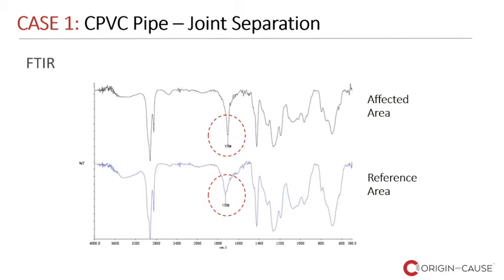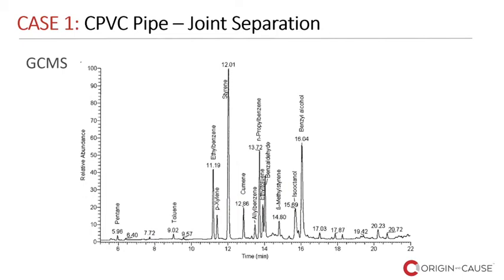It basically helps us understand what the material is made of, and not only that, but what deviations from the standard there can be, or what contaminants can be on the surface. In this case in particular, we wanted to know whether the contact cement had degraded prior to being put in use. We were able to do that by looking at the blobs of contact cement that were left over on the pipe. Or we can use more complex and specific techniques such as GCMS, or gas chromatography mass spectrometry,